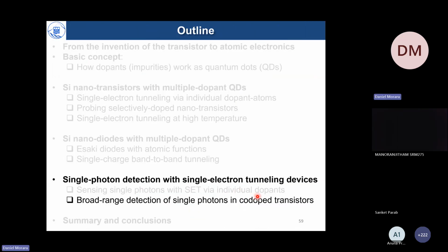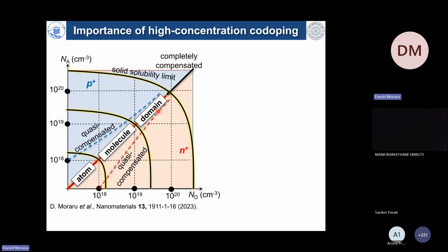More recently, we looked at the co-doped transistors, which are very highly doped. And this work is done again with IIT Roorkee colleagues. It's very important for us to understand that co-doping can build a new type of materials. If you are co-doping at low concentrations, ND and NA, we can create atomic functionalities. If you dope in the middle range, you can create molecules. If you dope at high concentrations, close to the solid solubility limit, you can create domains, or areas which are either N-type or P-type. And if you dope in an equal concentration, you can compensate almost perfectly, but please be aware that it's never fully compensated on the nanoscale.